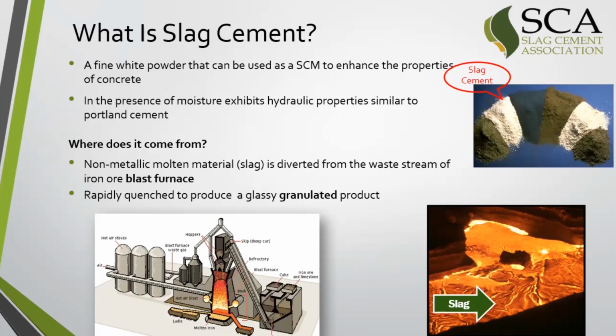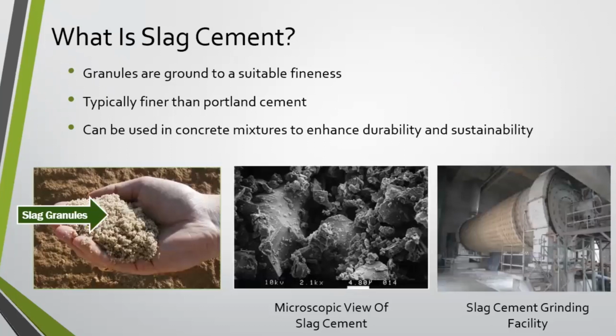Where does it come from? So steel production, you need an iron ore blast furnace. And basically you've got the molten iron ore, and then you've got a waste stream of this slag, which is the waste product. And so as this is diverted, that waste product is quenched, and then it becomes this glassy granular product. That's not the end of the process, but that's what we start with. So you've got these granules, and as you're looking to your left there, you see the granules. They're ground to a suitable fineness. And you might ask, what is a suitable fineness? Well, it's typically finer than Portland cement. And this can be used in concrete mixtures to enhance durability and sustainability. Does all sorts of good things in your concrete mix.